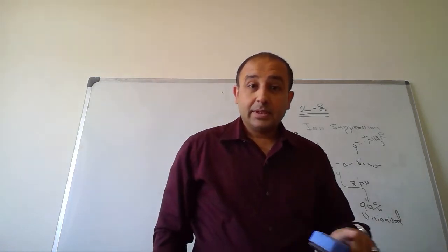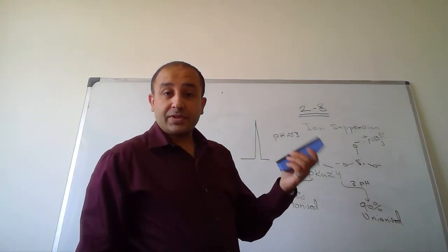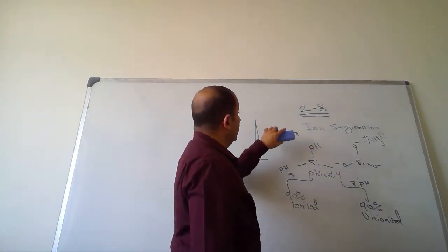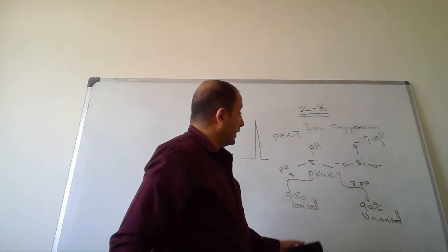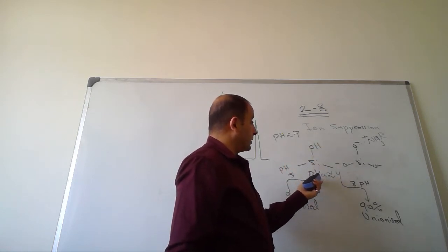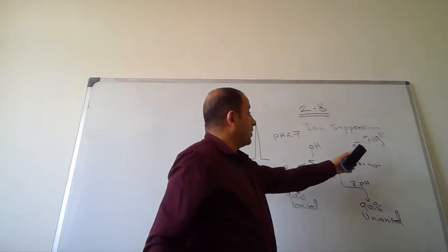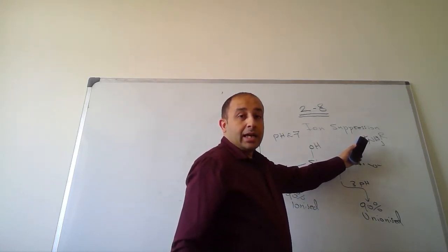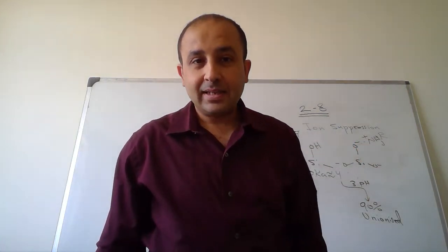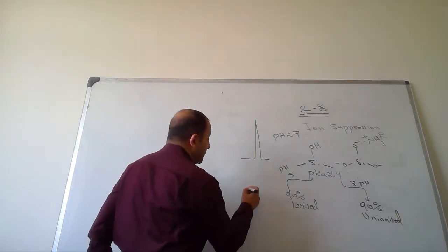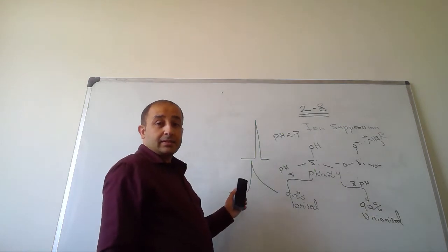On the other hand, if the mobile phase pH is above 6, for example neutral pH, in this case the majority of silanols, due to their pKa's, will be ionized. So silanol will prefer to make a salt bridge with analytes, and this will induce some sort of tailing, as we discussed last time.